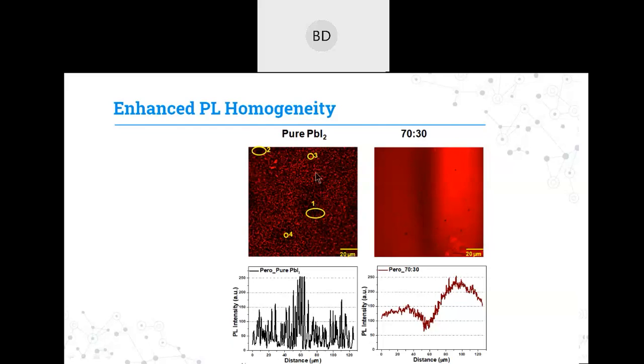But if you see spots number 3 and 4, which are bright in illumination, some grains are illuminating very bright. This is because these grains may not have a connection with the nearby grains. So when you shine light on this film, the charge carriers are generated in these grains, but the charge carriers are not able to diffuse into the nearby grains. If they are not able to diffuse, they will be confined within the grain, and when the recombination happens, it will be a perfect recombination and gives very good luminescence. Like if you see in the intensity range, some bright spots are covering a range of 250. But this kind of emission from the perovskite film is not a very favorable condition, because of the disconnectivity in the grains.